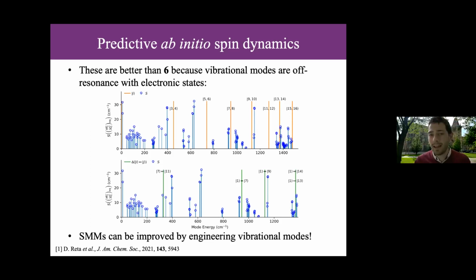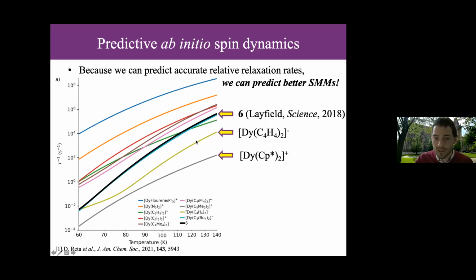And so these plots show us here the transitions from the ground to any pair of excited states, these orange lines, and these green lines are the low energy transitions between different excited doublets. And so you can see for almost all of them, they are not resonant with the calculated vibrational energies, which are these blue sticks. And so that just happens by circumstance. And so what you find is that the barriers aren't actually any bigger for these two. In fact, you can see the slope of this gray one is considerably less than the black one. So the barrier isn't any bigger. But essentially the prefactor in your Orbach term, the tau naught, which comes from all your vibrational stuff thrown into this constant, is orders of magnitude slower. And so you get far, far slower relaxation.